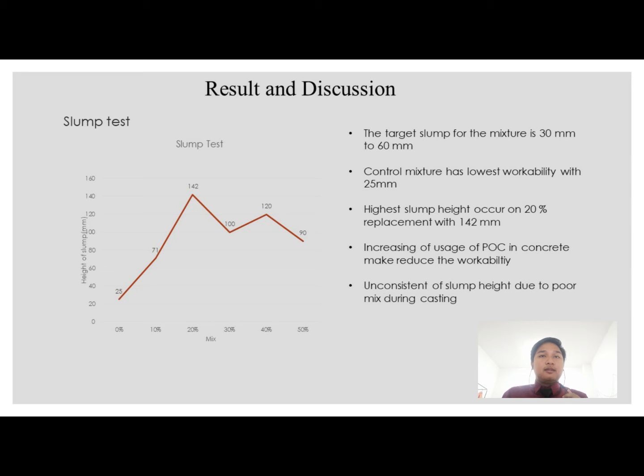From the graph we can see the lowest slump height is the control mixture with 25 mm. The highest slump is at 20% replacement with 142 mm. We can see from the graph that increasing the usage of POC in concrete reduces the workability. We can see the trend after 20% to 50% use of palm oil clinker.